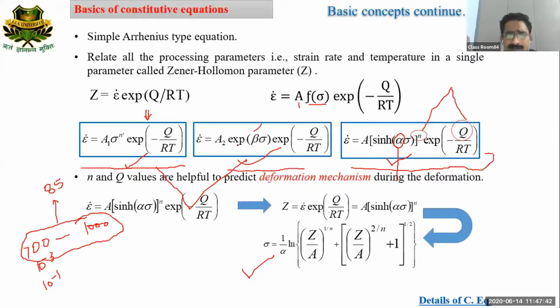With the help of n dash and beta, we can calculate this value of alpha, and with the help of this particular sine hyperbolic equation, we can have the value of n as well as the value of Q. So by getting all these values, we can put those values back into this equation and develop a standard equation. In that standard equation, when we put in any temperature or strain rate, we can get the value of flow stress. In this way we can generate the data within the deformation window for any particular set of conditions where we have not performed any compression test.